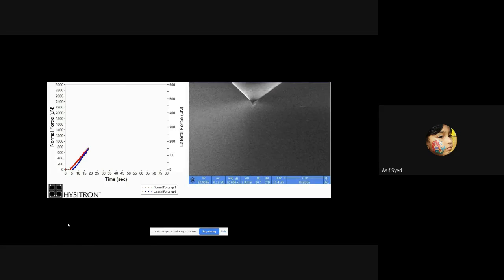At some point, you can see the material will come off from the surface, and you can calculate what is the load. So you saw the crack formation. You can see that load drop here in the load displacement curve, and the material got removed. You saw the big load drop.